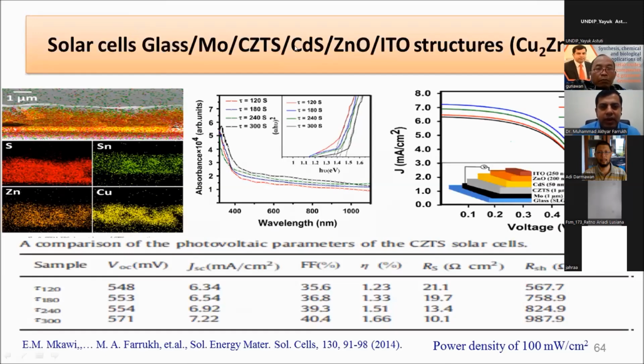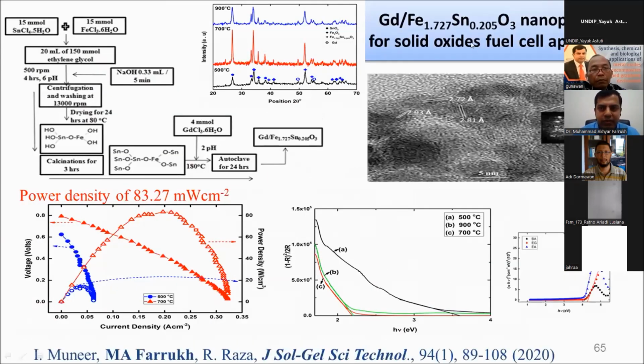Now this is one of the nanocomposites we have used, and the percent efficiency is calculated. This power density is 100 milliwatt per centimeter square. So this is one of the complicated long metal oxide materials. We have converted it into simple oxides by using the ternary metal oxides, and then you can see the power density is 83.27 milliwatt per centimeter square. So actually we are now exploring different solid oxide fuel cells to act as power generation. So you can use it as a solar cell or photovoltaic cell.